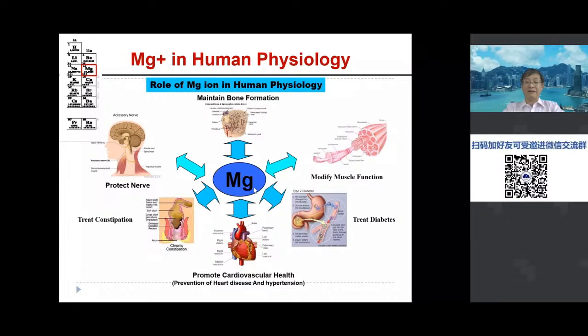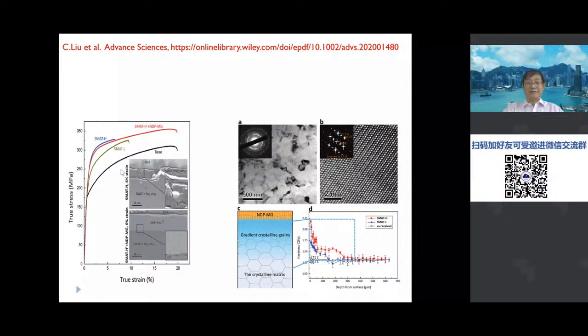But as I just said, the first material we developed has a composition of magnesium, copper, and yttrium. So this component may not be biocompatible. For this reason, for this particular application, we have developed a new alloy, which is composed of magnesium, calcium, and zinc. All these three elements are necessary for human physiology, and if we adjust this composition adequately, we can obtain this new structure, metallic glass with nanocrystals. Okay?